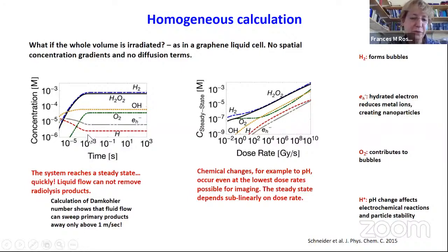Given the speed at which things form, it's clear that liquid flow can't remove radiolysis products unless you could flow at 1 meter a second. The other thing is that the steady state concentrations depend on the dose rate. And even, so we used 10 to the 7 before, even if you reduce the dose rate really low, it's still going to be quite an effect. You cannot image with so few electrons that you don't change the chemistry. Okay, so this is sounding a little bit grim, right? It goes bad immediately, and however low the dose of electrons, it's not low enough to make things better.